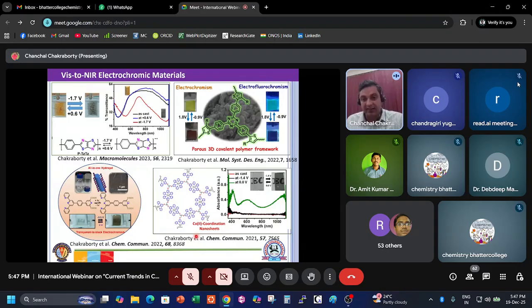As this is a covalent polymeric structure that intrinsically has pores, the ion diffusion is very swift, and we can get very fast bleaching time and coloration time. A very stable system basically. We studied the stability, and most importantly the solar light block. The full solar irradiance is blocked by 68% when we use the fully reduced state. And the coloration efficiency we got is 183 centimeter squared per coulomb. This is not so high, I can tell, but it is moderate. But the power and energy consumption for this kind of electrochromic film is very low. But the thing is that we cannot block the sunlight to the fullest.